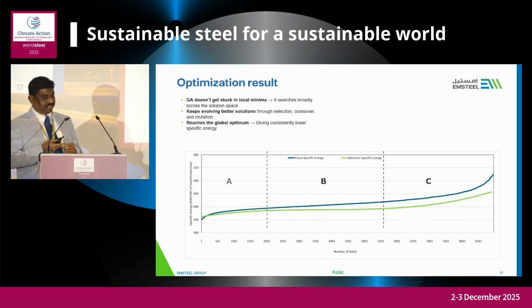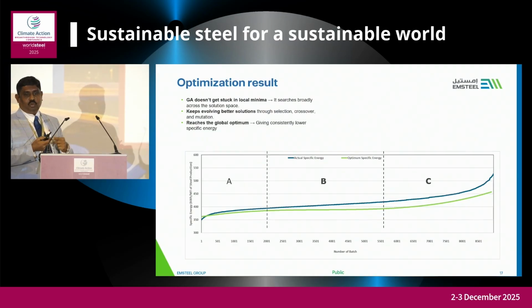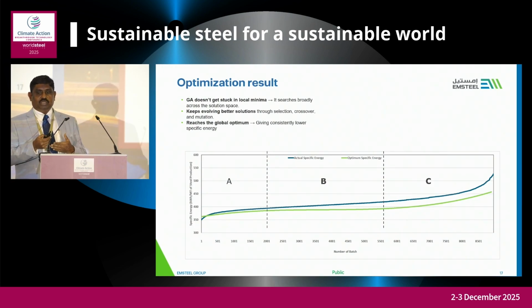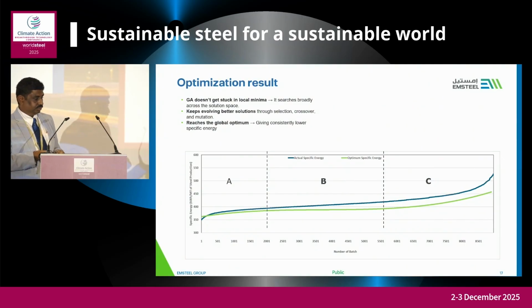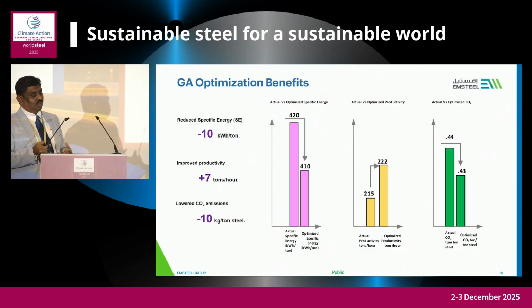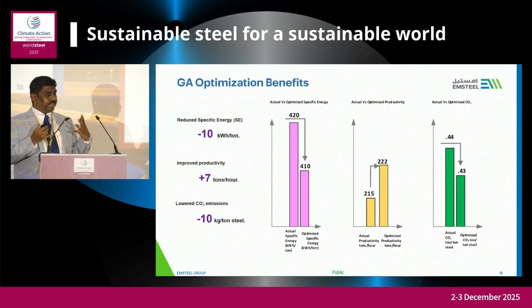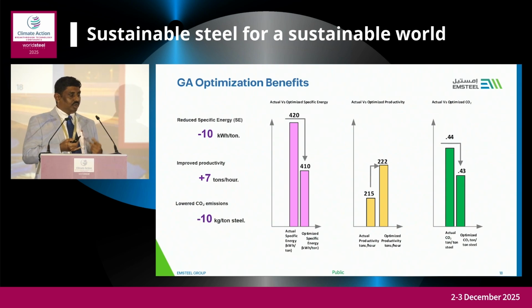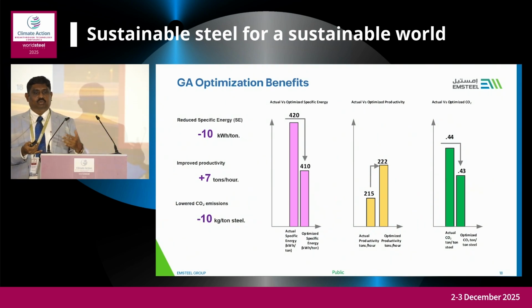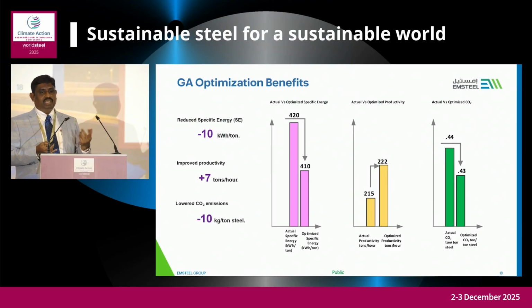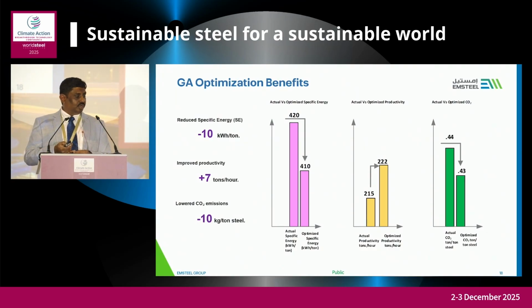And another thing here, if you see the result, we divided the result into actual versus optimized. In some cases the GA does not reduce because it is already optimized. In some cases, it tries to reduce the energy, and based on the energy reduction, it selects the four parameters which can be controlled, which will reduce the energy. Then after this result, we considered the whole year data, and we are able to reduce 10 kWh per ton of steel, and you can consider 7 tons per hour productivity. We convert this to CO2 emissions based on the country's kWh to CO2 factor, and it is around 10 kg of CO2 emissions reduced per ton of steel.